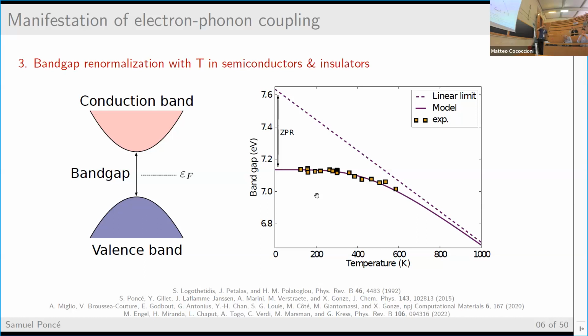The issue with this one is that the renormalization of the band gap is directly linked with the real part of the electron-phonon self-energy. And you can show that this real part has two terms. One is the Fan term, the Feynman diagram that you've seen, but there is actually another diagram, which is the Debye-Waller. The Debye-Waller is a second-order derivative of the potential with respect to two atomic displacements, but then you sandwich that with two unperturbed wave functions. This is as opposed to one first-order wave function and first-order potential, but they are at the same order. And this is a static object, so it's actually real. So when you are looking at things like the imaginary part, the line width and so on, you don't care about that term. But in this case, the real part is very important. And the issue is that to compute that term, you usually need an infinite number of empty states.